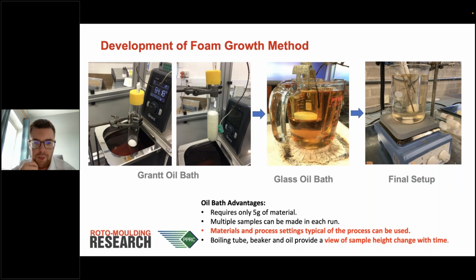The advantages of this were that in my particular case, it only needed 5 grams of material instead of probably around 2 to 3 kilos of material for a small cube mold on the ferry machine. It also meant that you could scale up the experiment so that you could make multiple samples under the same heating conditions if you wanted to. And because it was digitally controlled, you were able to create a comparison between the industrial scale equipment and my experiment.